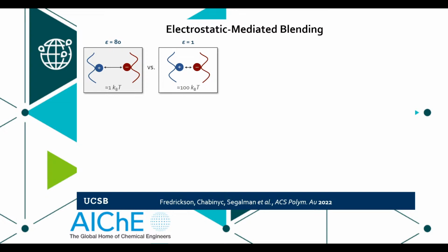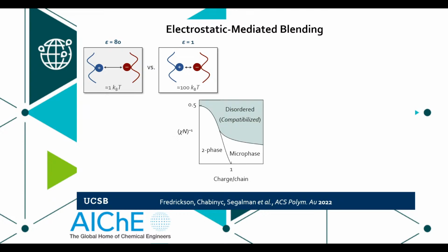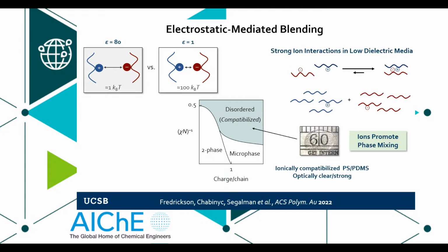My colleague Glenn Fredrickson figured out that, if I remove the solvent after I process it, those ionic interactions become extremely strong because the polymer backbone is actually a very, very low dielectric environment. That will even allow the charges to attract with 100 kT of interaction strength. And so it could be a great way for creating miscibility in systems that otherwise would not work this way. In fact, even at very, very low charge loadings, we can make completely immiscible polymers like styrene and silicone mixed together, right? So can we use this concept?